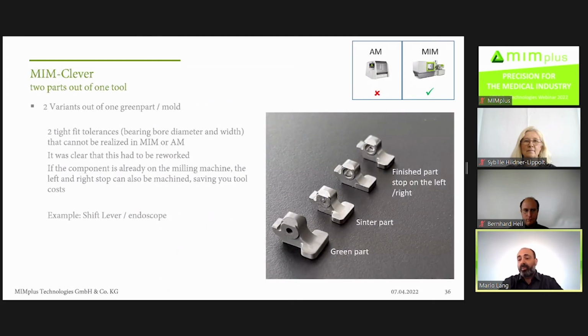MIM clever, 2 parts out of 1 tool. The part you see here has some really tight tolerances. We have a fitting tolerance on the bearing bore diameter and on the bearing bore width. So it was clear that if we use MIM or AM, this part needs a secondary operation. So it was clear we have to do the machining.